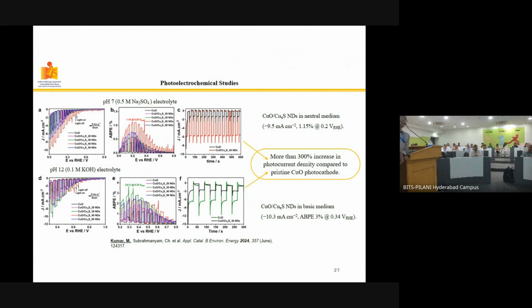And in all other studies, as I mentioned, I'm not a fan of doing these things under highly alkaline conditions, because this is not very practical. Many a time you report good efficiencies, but you get a question that you have a hole scavenger which is actually playing into it. So then you look at this under neutral conditions, you look at all the combinations you can think of, and you try to vary the loading of, for example, the nanorods, the disk kind of thing.